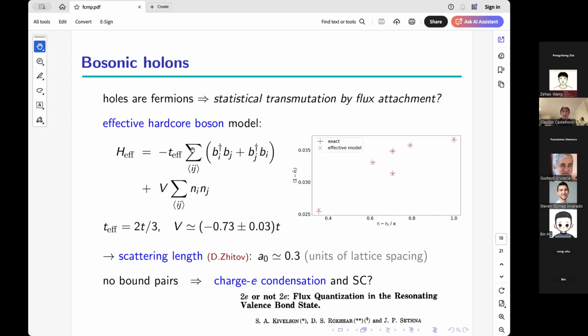And by doing a fit on the interaction V, this was the work done by the undergraduate student Daniil, you can see that V is slightly attractive, if anything, and then the exact result from the previous slide is in the pluses here. The effective model gives you the crosses, and it clearly shows that you can capture the behavior very well with just a